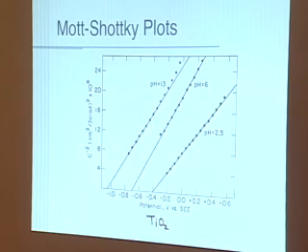And then, of course, I know the redox potential from whenever I put it in solution. You will notice that in the case of TiO2 this band edge is pH sensitive. It's just 60 millivolts approximately per pH unit, which has to do with protonation and deprotonation of the metal oxide surface here. According to the Mott-Schottky equation, all these lines are parallel to each other because they depend on the semiconductor dopant concentration. You can see there's a little problem there, but we won't get into that today.